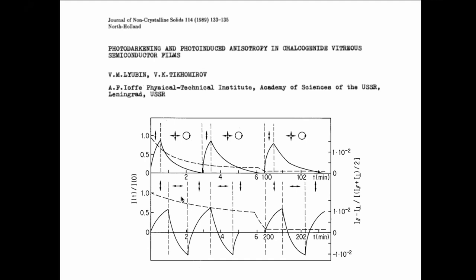The anisotropy occurs near the band gap energy — slightly below it, for bulk glass where the light must penetrate a few millimeters, requiring low absorption. For arsenic sulfide with a band gap of about 2.1–2.2 eV, this was done with red light. People sometimes call the three-coordinated and chain-end defects C3+ and C1- defects, or self-trapped excitons, though excitons are more associated with crystalline materials.